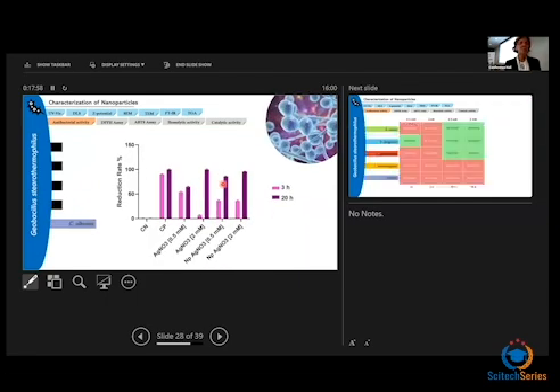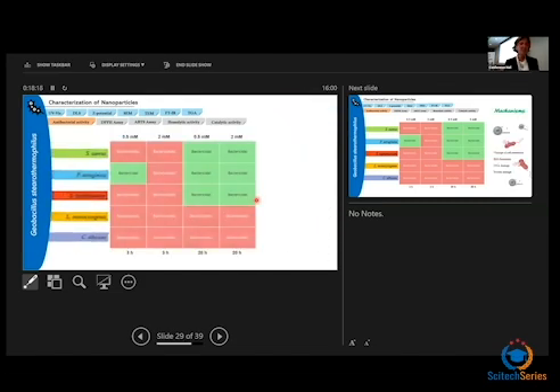And similar results were also obtained for Candida albicans, where we could observe, in comparison to the control cells, a reduction in viability, but not complete removal. Overall, these results, which are summarized in this table, show that the nanoparticles have a strong antimicrobial and antifungal potential. And we also could verify that the concentration of nanoparticles that we used was in some cases lower than those reported in the literature, thus confirming a good potential for their use as antimicrobial agents.